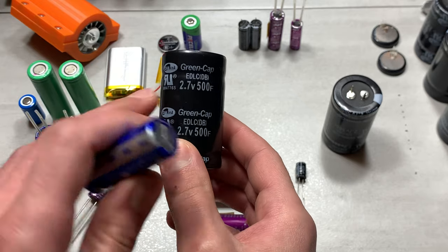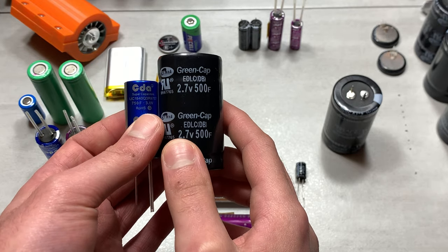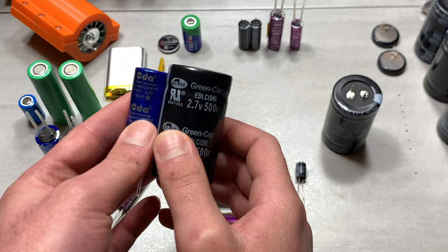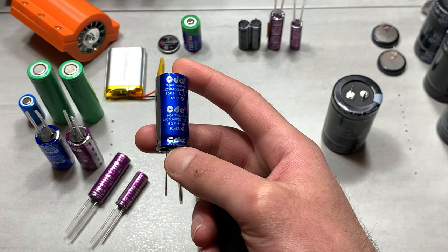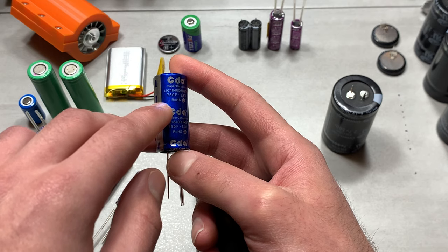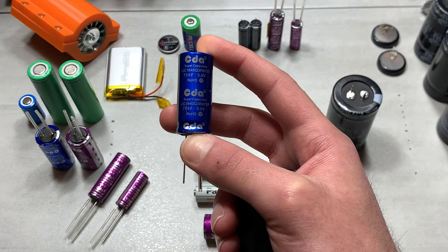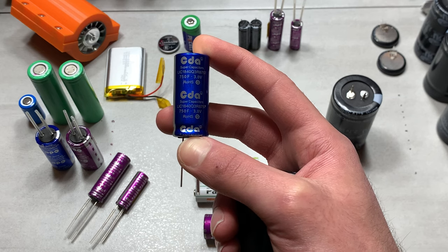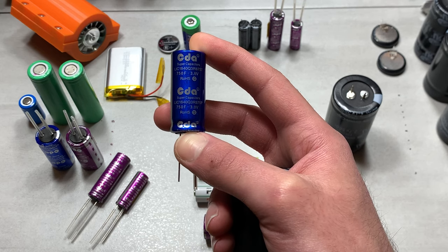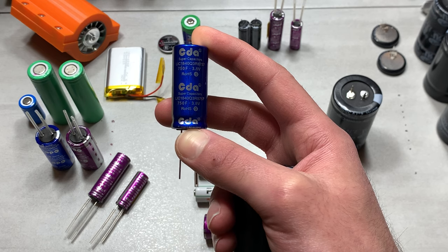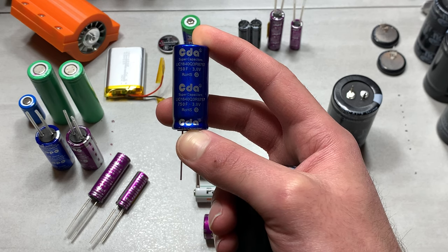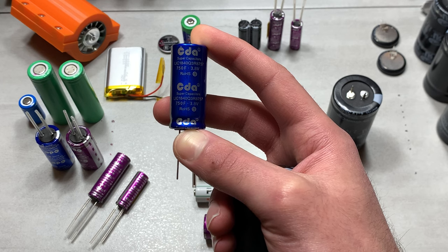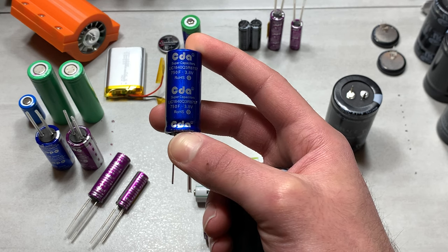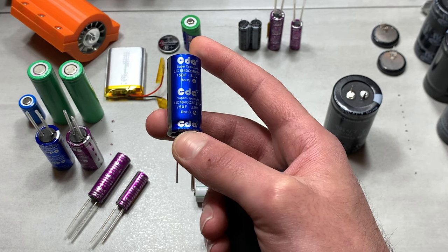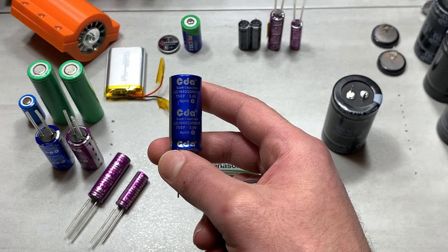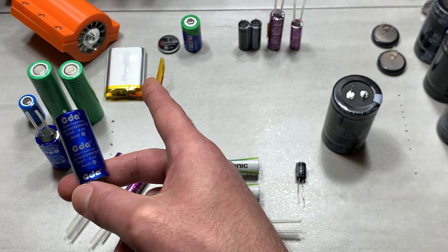So again, that was only for the case of EDLC, or electric double layer capacitor, defined as generation 1 in the book. Generation 2, which they called LIC, or lithium ion capacitor for short, consists of a graphite anode, an activated carbon cathode, and a lithium ion containing electrolyte solution, where lithium ions intercalate and deintercalate in and out of the crystal structure of the graphite particles and the activated carbon particles, depending on whether you're charging or discharging. A process which is very, very closely mirroring that of standard lithium ion batteries.